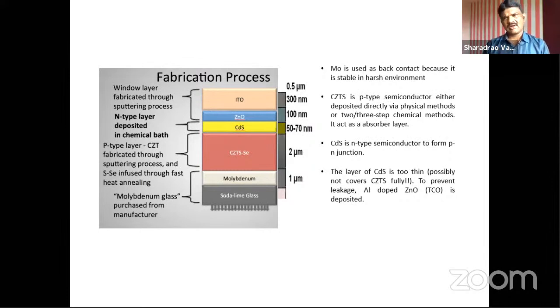on which we can deposit CZTS, or people can deposit CIGS material or perovskite material, which is a p-type semiconductor obviously, which can be deposited by physical methods or chemical methods, and it acts as an absorber layer having a thickness of about 1 or 2 micrometers. Lower thickness is okay because they have a high absorption coefficient, on which we have to deposit n-type semiconductors. This n-type semiconductor may be CdS. We have to deposit a very thin layer of CdS. Many times, this thin CdS, having a size of about 100 nanometers, is not sufficient to cover the total CZTS. That's why, to prevent the leakage, we deposit aluminum doped zinc oxide, which we can say is a TCO, over the CdS, and on which we can use the ITO layer.